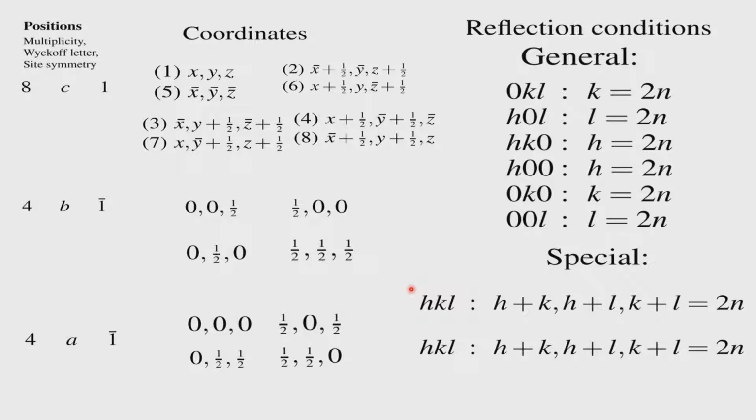See, once you have these unusual systematic absences coming up, since you have not done the structure, you see these are coming up because now you know where the atoms are sitting, in this special position. It does not tell you the structure information. You still do not have x, y, z, that is what you have to determine. But before you even determine the x, y, z, you know in this particular case the atoms have to sit in special conditions and follow this systematic absence. So it is an advantage.